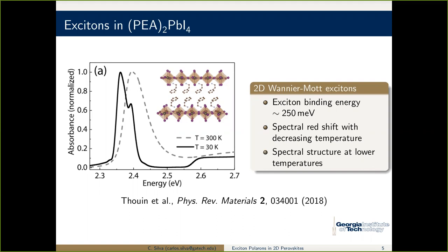This has been discussed since the 1990s for these materials. And there is a very reasonable argument that this has to do with spin exchange. There's some degeneracy associated with spin exchange that gets lifted. You would expect three peaks if that was the whole story. There's been speculation about the Rashba effect, relativistic effects. If you're an electron in an asymmetric potential and there's strong spin-orbit coupling, you get accelerated to relativistic velocities. You generate a local magnetic field that lifts spin degeneracy. And that has been argued. And in fact, the spacing of this has been presented as something that might be consistent with that.